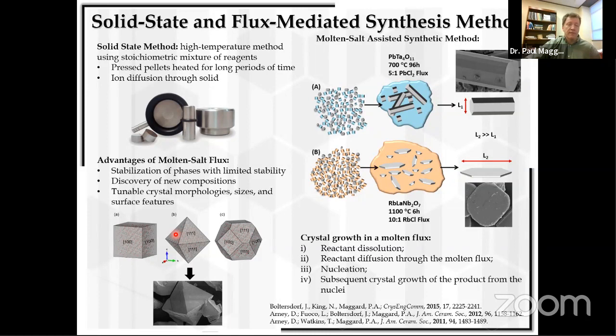So one of the methods that we use as an alternative to the simple solid state method, which involves simple grinding and heating of the materials at high temperatures, we use molten salt fluxes. And molten salt fluxes help with the solubility of oxides to dissolve them, and then to recrystallize them into different morphologies and different sizes,